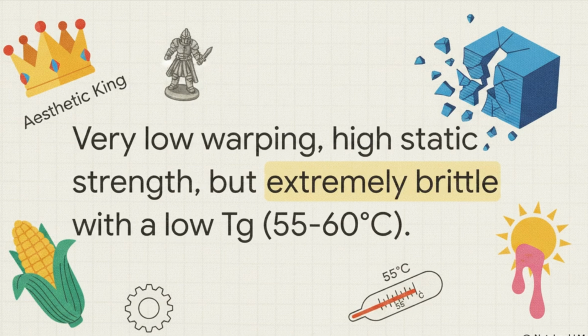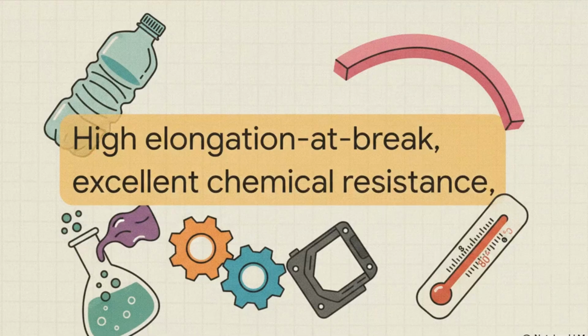Plus, remember our glass transition temperature? PLA's is a super low 55 to 60 degrees Celsius. Oh, and it degrades pretty quickly outdoors under UV radiation. So definitely the absolute go-to for complex visual details, prototypes, board game pieces, but keep it inside and keep it away from heat. Next up, we have PETG, the tough all-rounder.